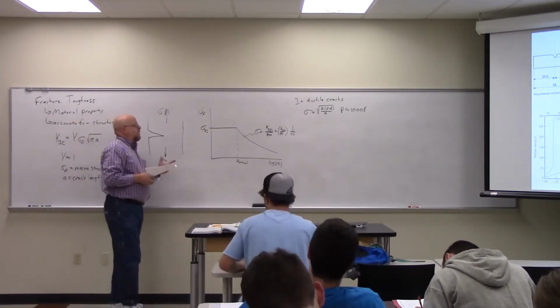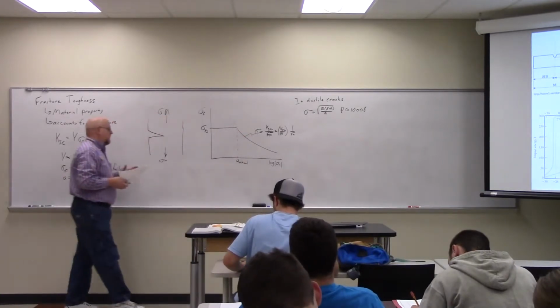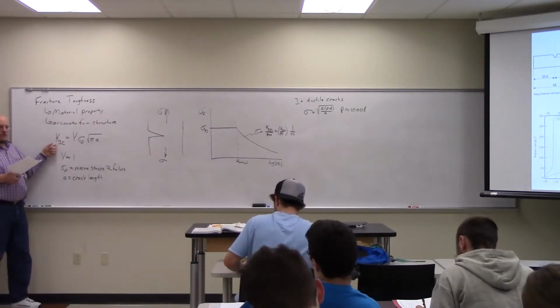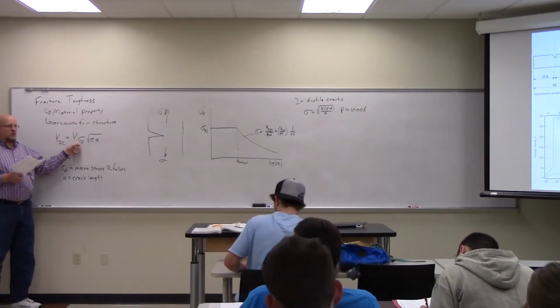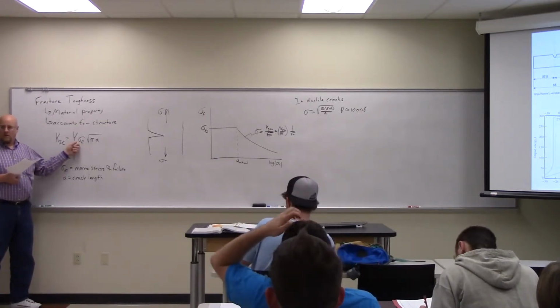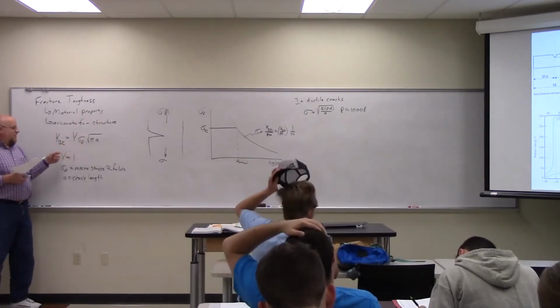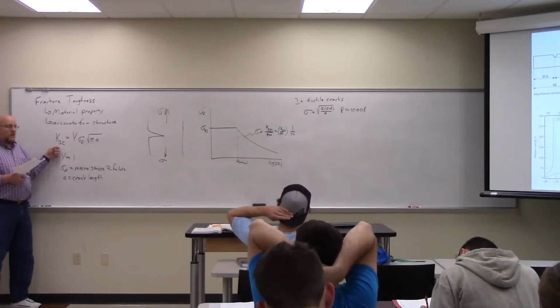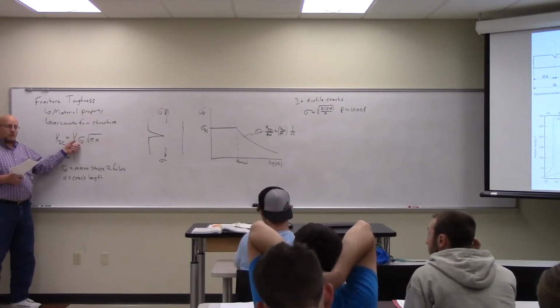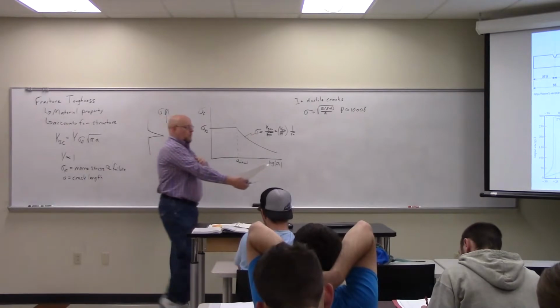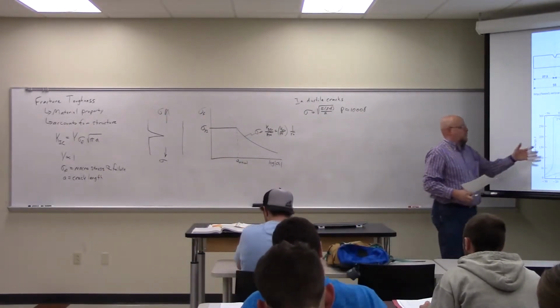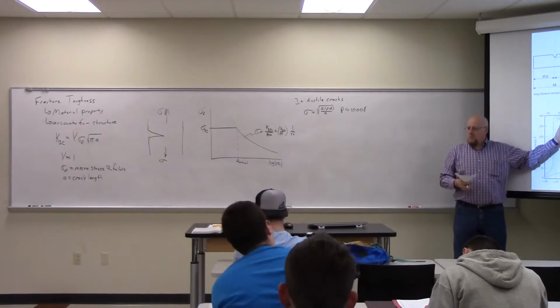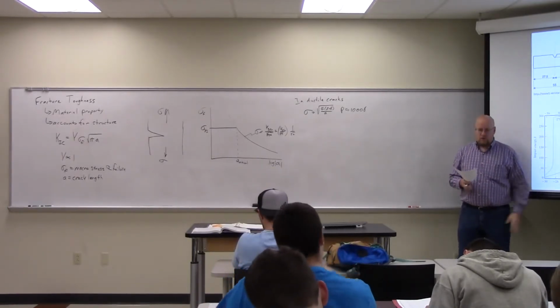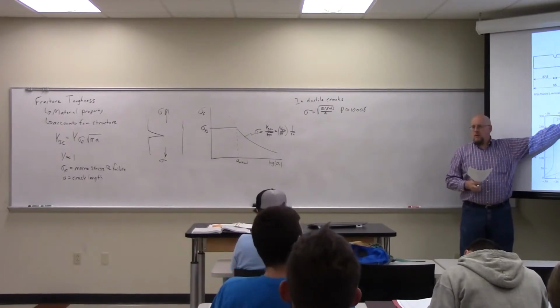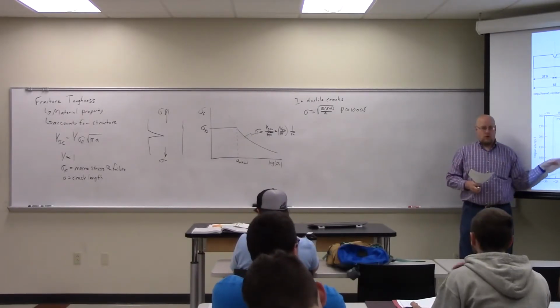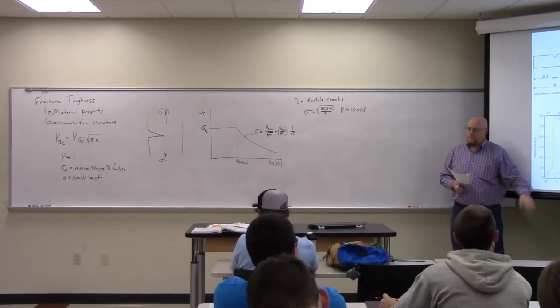Okay? So if you have something that has a low K1C, a low fracture toughness, that means it takes a small stress for a given crack length to break it, which means it's brittle. If I have a large fracture toughness, then it requires a large stress to break it, and so it's ductile. So effectively, the impact energy in the Charpy test is measuring, at least qualitatively, the fracture toughness. Here we have a high fracture toughness, here we have a low fracture toughness. Ductile, brittle.